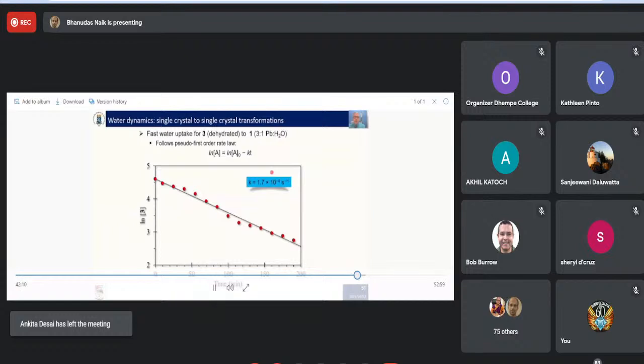And my student, in fact, has calculated basically on the intensity. And so this is the concentration of 3, the dehydrated compound. You can see that 3 decreases here with a 1.7 times 10 to the minus 4 seconds minus 1 rate constant. He was using a simple pseudo first order rate law because we brought the water.